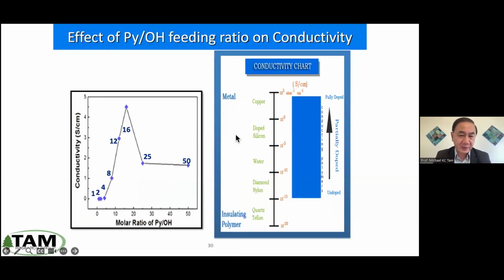What was done is that we looked at the ratio of the pyrrole monomer to the amount of OH groups on the CNC. As you can see, we measure the conductivity. Our result shows that with a ratio of 16, you get the optimum conductivity. An insufficient, lower amount results in insufficient coating, so you get poorer conductivity. Too much results in multilayers, and you get delamination. So the optimum we found was 16. So we were able to convert an insulator, which is a wood fiber, into a conductor that's near the region where it can conduct electrons.